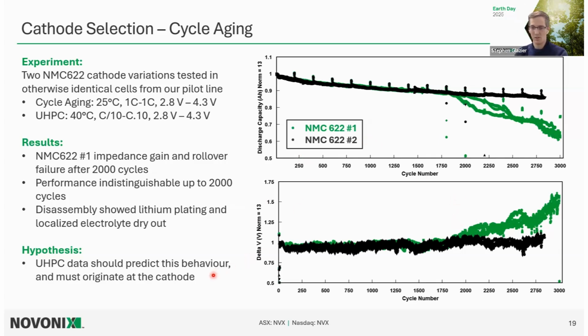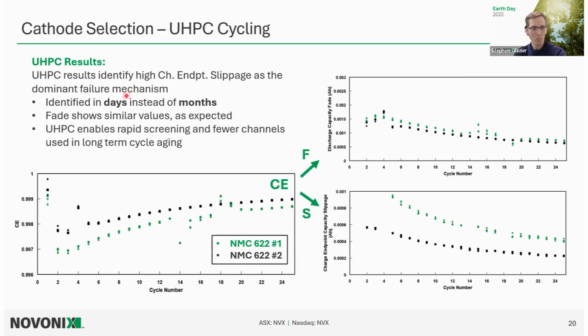So the hypothesis here is, can we use UHPC to do this? How quickly can we detect whatever's happening here with UHPC? I'm showing here, also on 1 amp hour pouch cells, just 20 cycles of UHPC done at a slow rate. What we're really trying to do here is measure the electrochemical effects and not the kinetic effects happening.